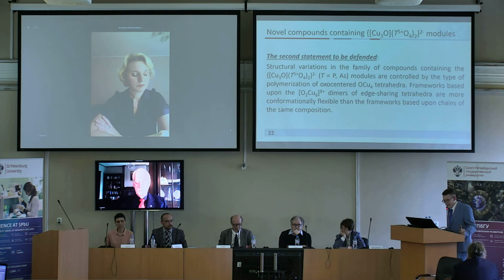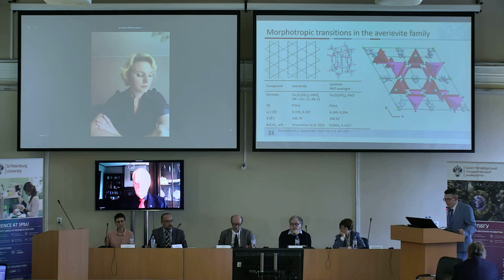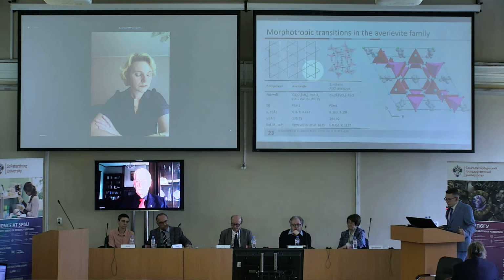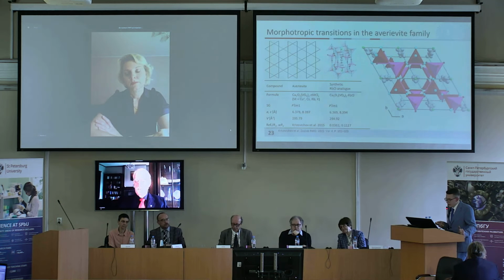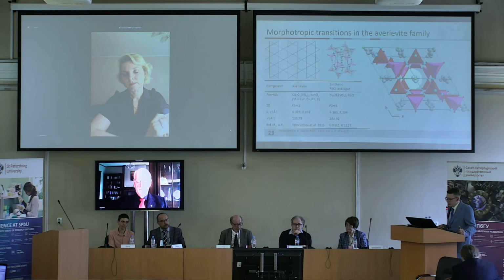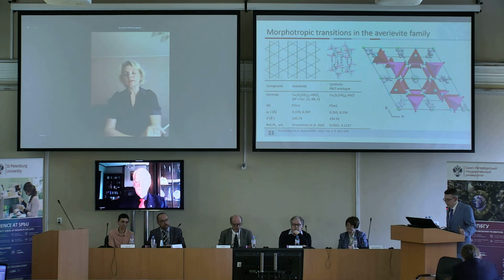Frames based on the dimers have greater conformational flexibility than frames based on chains of the same composition. The second object of structural study was the structural type of averievite, which is characterized by the presence of copper atoms, layers of oxo-centered tetrahedrons alternating along the C direction, forming channels filled with alkali metals and chlorine atoms.